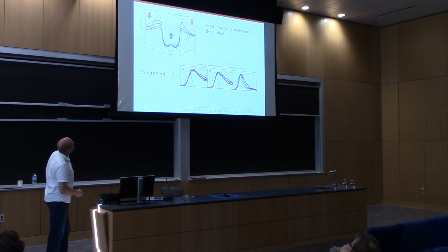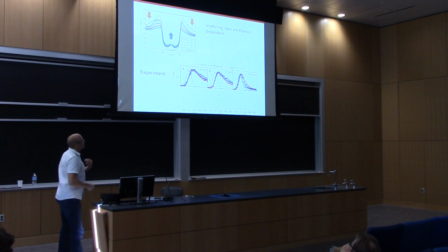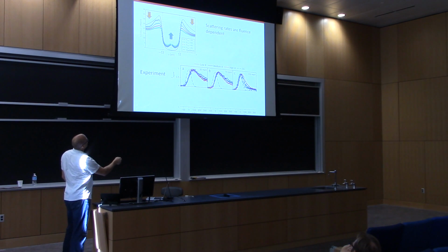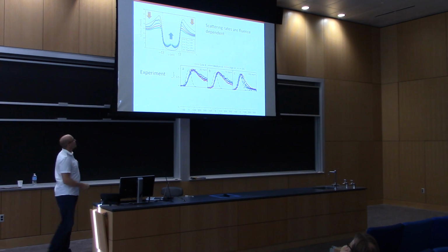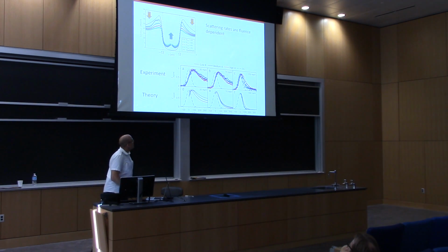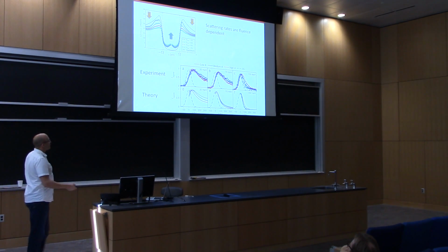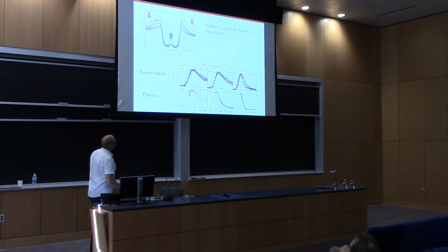And this is the theory picture we had. This is the experiment, where the relevant phonon lives at roughly 70 millielectronvolts. Now, if you look below, you can see that for low fluence, the blue curve here, this is fast, slow, and the red one is fast. Above, we've got the opposite. For low fluence, I have very fast relaxation, and for high fluence, the red curve, I have slower relaxation. So this somewhat agrees with our picture, and in fact, we can play with our parameters a bit and end up with something that looks very much like their results. Sort of a kink, or change, at 70, and sort of similar colors as you go.